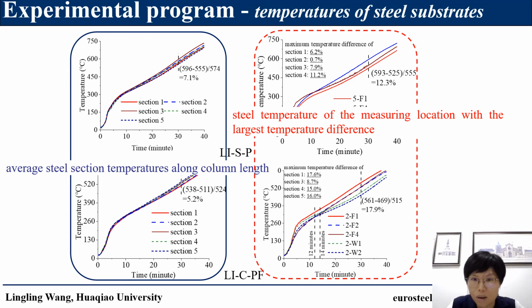In most cases, it's above 10%, taking thermal stress and thermal bowing into consideration, particularly if a column is slender and subject to a high load ratio. A 10% temperature difference may have significant adverse effects on column stability. It is difficult to discern a pattern of temperature distribution due to the random nature of intumescent coating cracks. Therefore, if a non-uniform temperature distribution is considered in analyzing columns, the most unfavorable temperature distribution should be assumed.